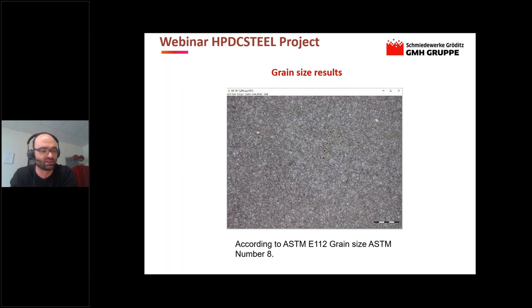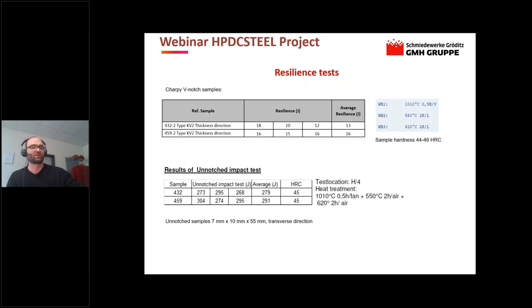So this is also the basis for mechanical properties of the steel, which finally determine the die life of the die steel and of the die casting in the final application. All these metallographic results must bring about good mechanical properties, for instance, the toughness. Resilience tests were made in this case for Charpy V notched samples, but also for unnotched samples, on the block top as well as on the block bottom in the core part, but also halfway between surface and core.